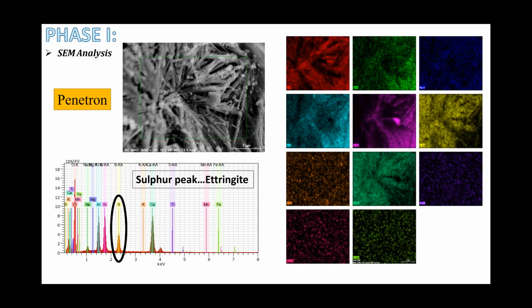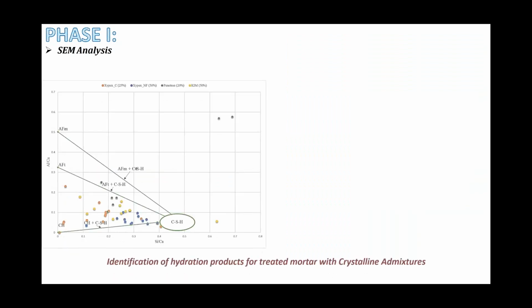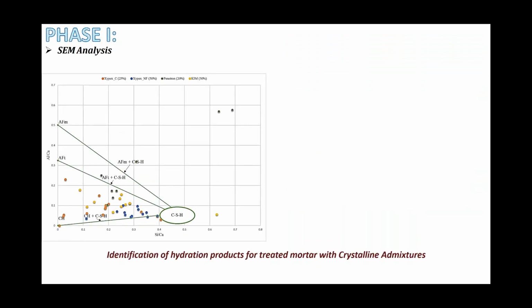And similarly, I plotted the elemental mapping for these products. And also, to find the hydration products, I plotted the aluminum to calcium ratio and also the silicon to calcium atomic ratio to identify different hydration phases inside the material. As you can tell in here, it's kind of spread around, but still they are aligning along the line of calcium hydroxide and C-S-H gel, which is the main product of the hydration, and C-S-H is also responsible for the concrete strength.